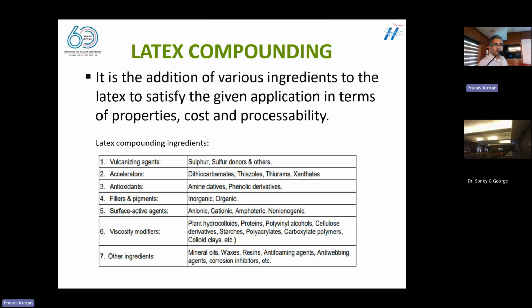So, as I told, these rubber products which we are using have to have a shelf life. When you use gloves, they have to stay on the shelf for a year or two. When you use a rubber tire, it has to stay on the shelf and also with the car or bus for a number of kilometers or years. So for this, it has to have air resistant or ozone resistant properties, which are imparted by adding other chemical agents called antioxidants. These antioxidants are scavengers which attack the radicals produced in the environment by oxygen or ozone, and they themselves get attacked by the oxygen and keep the rubber intact. So these antioxidants help the rubber to have shelf life for the entire usage period.